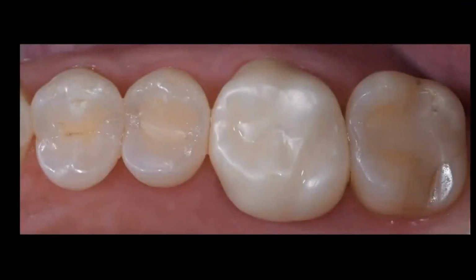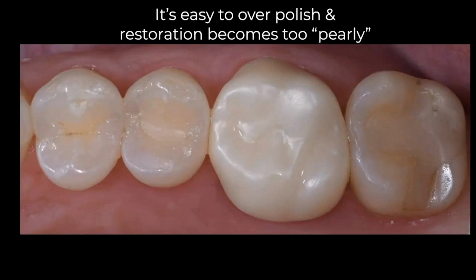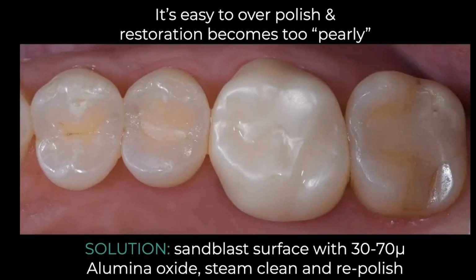Okay, so once we have now sintered the restoration and we're doing any post-polishing, it is easy to over polish zirconia, and when this happens, the restoration will start to look too pearly. So if that happens, it can easily be corrected. So how do we do that? You're going to sandblast the surface with 30 to 70 micron aluminum oxide, then just steam clean it, and then go ahead and repolish it.